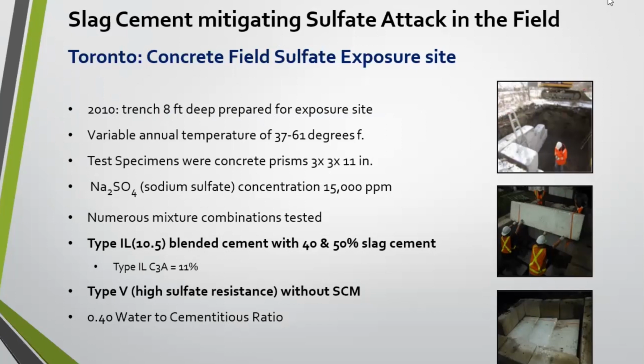Several different combinations of mixtures were used. The first being a Type IL, with 10.5% target limestone. The C3A content on the Type IL was at 11%. And then they used a type 5 without any SCMs at a 0.40 water cement ratio.